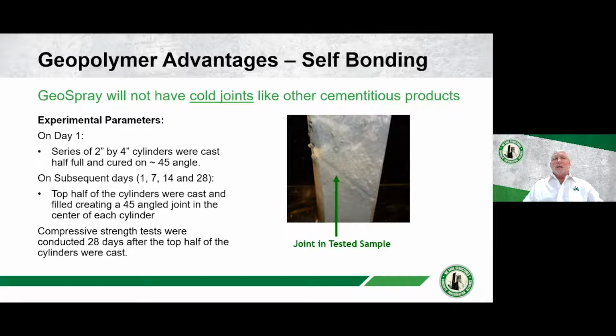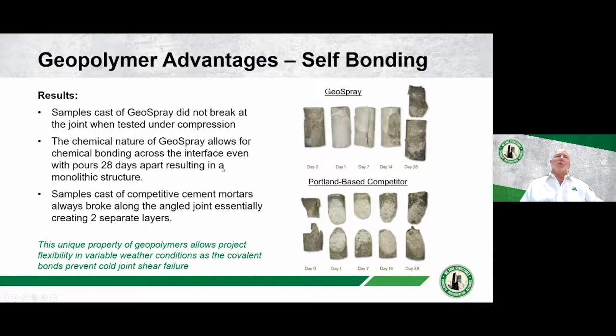Those cylinders were left to cure for another 28 days, and then a standard compression test was done on those cylinders. And the geopolymer material, when the compression test was done, all of those cylinders failed as a standard compression cone test. None of them failed along the joint line. If you do this with a regular cementitious mortar, you would find that the failure would be right along that bond line. So being a layered system with the geopolymer, if you go in, spray your system, come back, spray in a second layer of material, then you know that you're actually getting a monolithic bond there and getting a monolithic material.